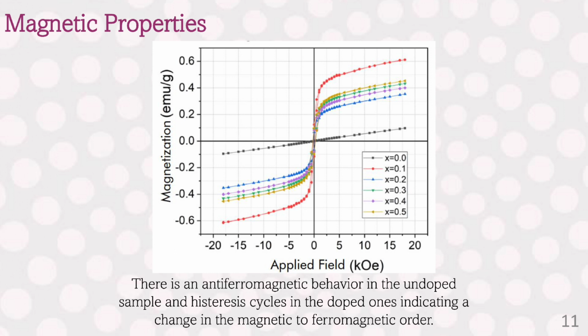To observe the magnetic behavior, with vibrating sample magnetometry, magnetic hysteresis cycles were obtained from the pellets, shown in the figure, where according to the mentioned crystallization, the undoped sample presents AFM behavior unlike the doped samples, which tells us that these cations induce a weak ferromagnetic order in the doped ferrite. In general, the results show that the magnetic structure modified by canting produces an inverse DM interaction, obtaining a change in the magnetic order from antiferromagnetic to ferromagnetic.